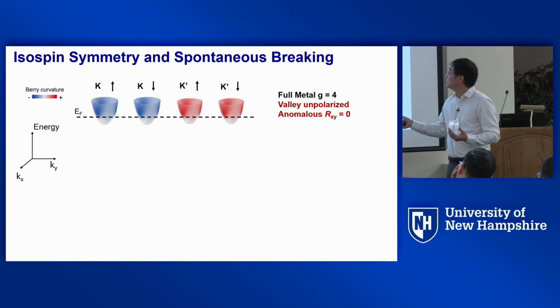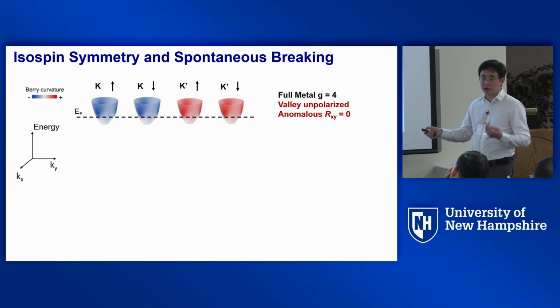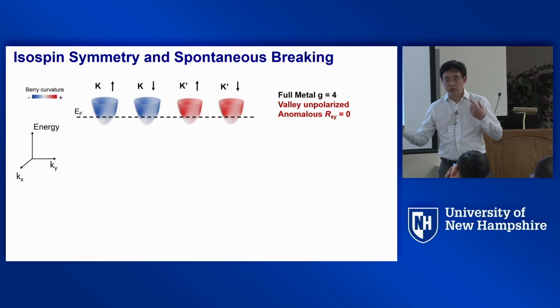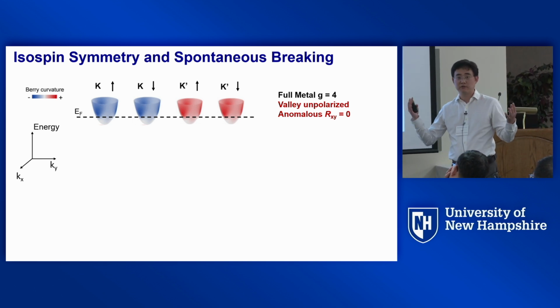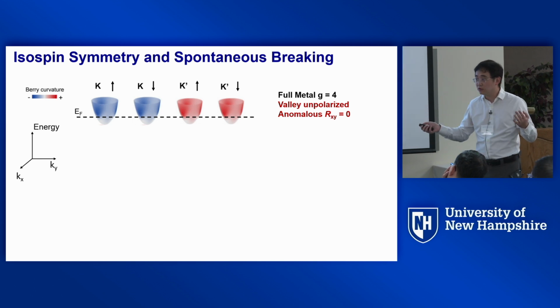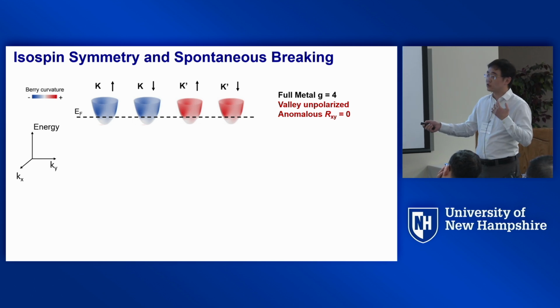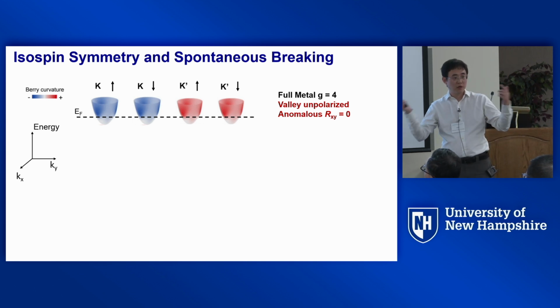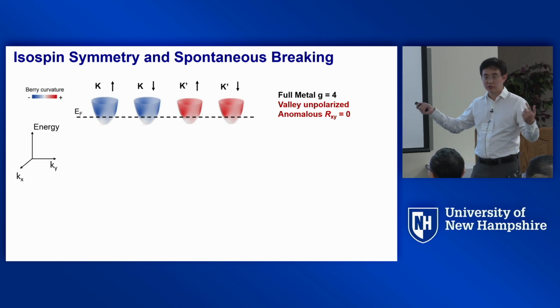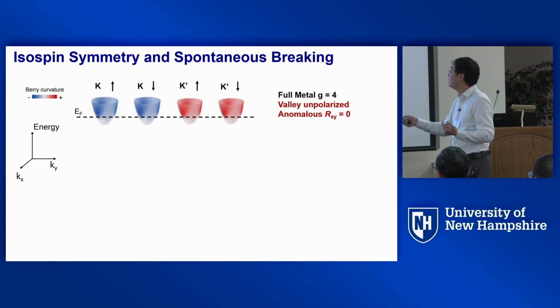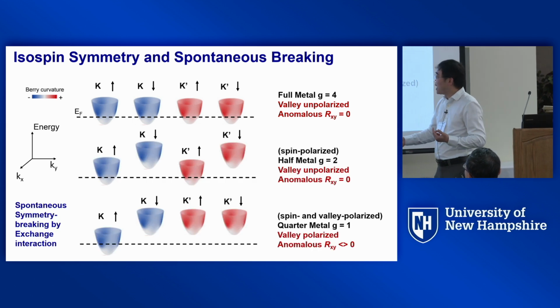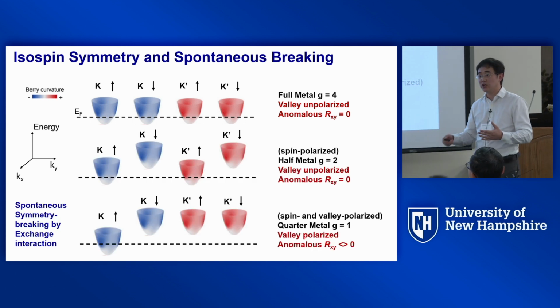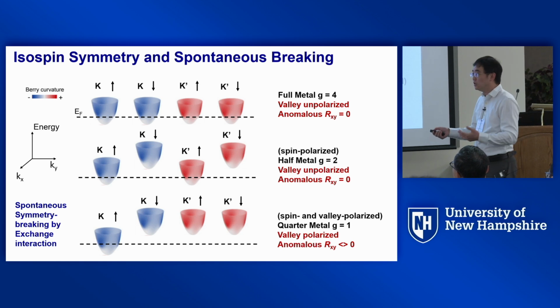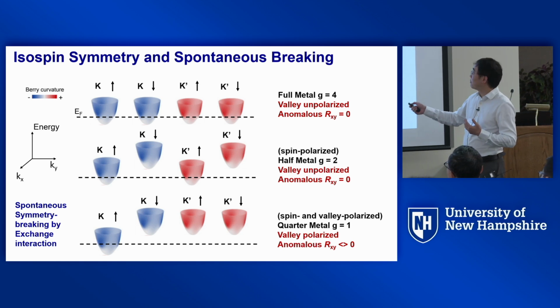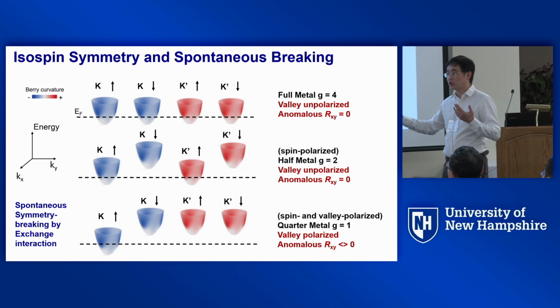In graphene, we know there are spin up and spin down. We know there are K and K prime valleys. So there are a total of 4 copies of any band structure at the single particle level. Well, if nothing interesting happens, all the 4 pockets are populated equally, and the anomalous Hall will cancel each other because there are time reversal pairs populated at the same time. However, when your band becomes really flat and the exchange energy is important, the degeneracy of these 4 pockets could be lifted in certain ways.